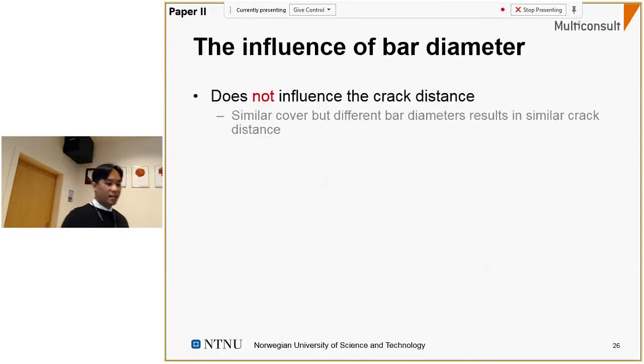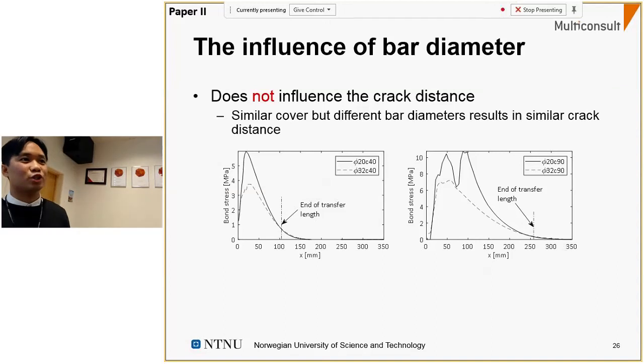Yes, I know that's a bit controversial with respect to what we actually know from before, but what is seen from these virtual experiments is that independent of your bar diameter, the crack distance will be the same. The bar diameter will only transfer the force to the concrete, but they need the same amount of length, independent of how large the bar diameter is, to induce cracking. So it's simply the spreading of the force over the cover that governs the final crack distance.